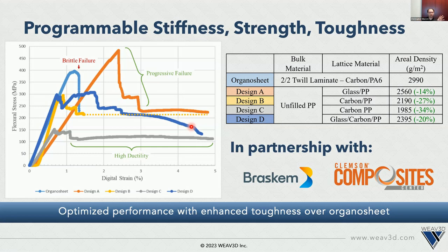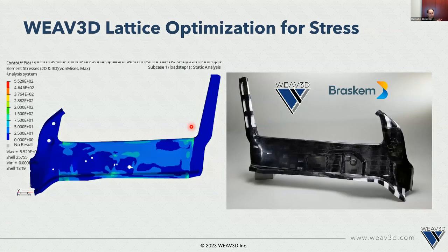So we took these flat panel results, and then we did FEA analysis on the actual part itself. And what we noticed is that there's a really high region of stress here in the middle of the part, as you would expect. This part is designed to be able to withstand a side pole impact on the passenger or driver's side door. But there's very little stress on the A and B pillars because these are glued into another component. So we actually realized we don't need a whole lot of lattice reinforcement in this area above and below that middle sash. We can effectively just use the middle area for the high density reinforcement, and then we can use less material in those areas that we know we're going to get trimmed out at the end of the day.